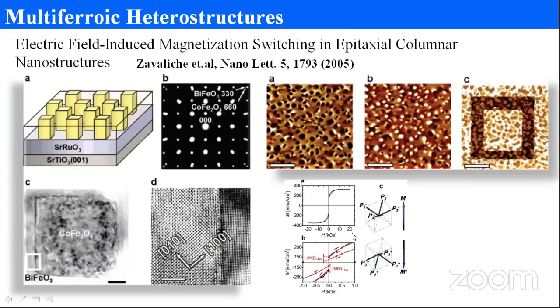Okay, so later on they reported on bismuth ferrite and cobalt ferrite nanocomposites, because as I said in the beginning, bismuth ferrite is much more electrically polarizable than barium titanate. Again this clearly shows that the bismuth ferrite and the cobalt ferrite are crystalline in nature, and the high resolution TEM clearly shows a very nice interface, and they are highly epitaxial.